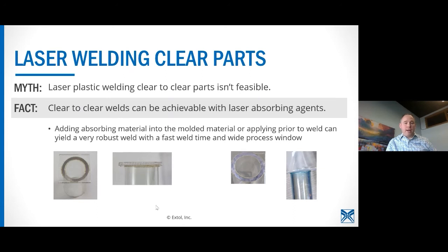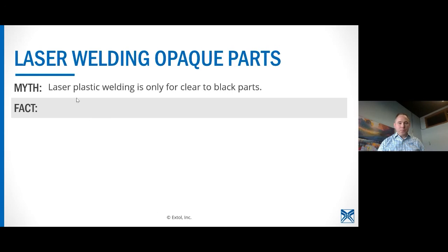And then the other item to be aware of with clear parts is 2 micron. Essentially what's happening with 2 micron, again, there's white papers out there on this, and that could have its own discussion, but both the top layer and the bottom layer of the clear are energized by the laser, and both are heated. So the process window, the way that that energy comes in, the optics to make sure that that's focused at just the right spot is key to that type of welding technology. And we've worked with a supplier of that wavelength laser to do those sorts of applications. So if you see that and you want us to take a look at that, we're more than willing and capable to do that. You guys jump in here if there's any questions.